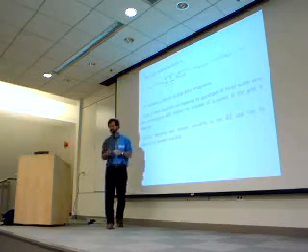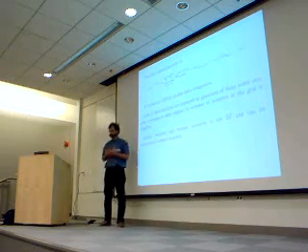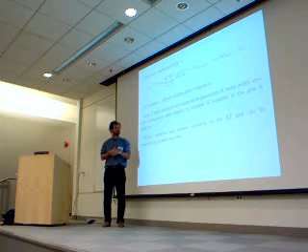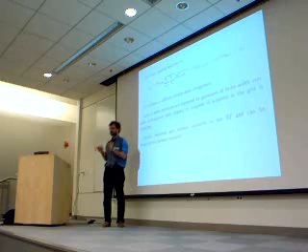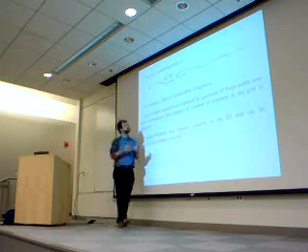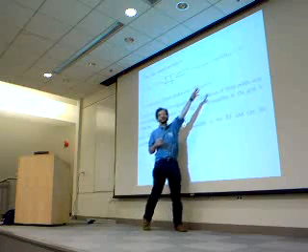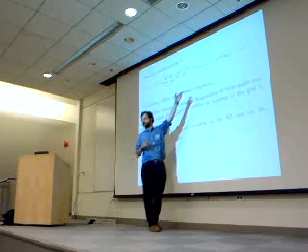So what we will see in the afternoon is that we will use some dense grid, but not enormously dense, and you will see that for the smallest smearing there will be some scattering in the results, which means that the sampling of the k points is not dense enough, such that many pairs of k plus q and k enter in the product of the deltas.